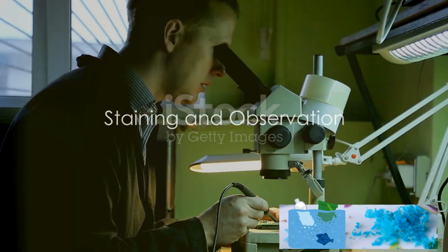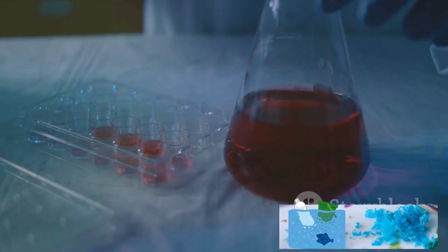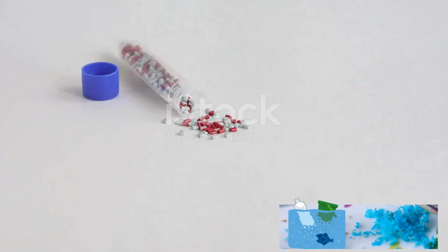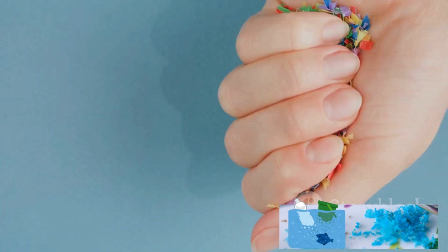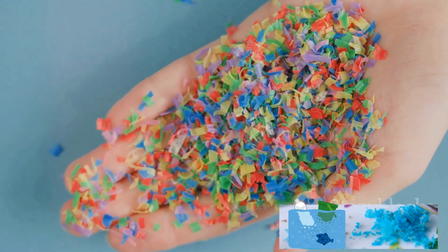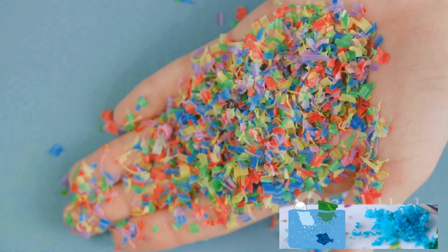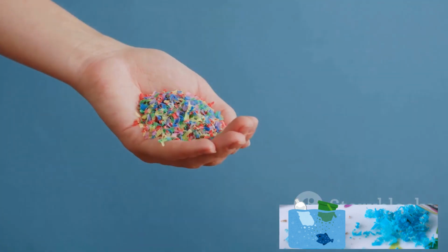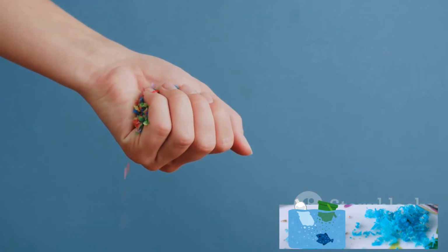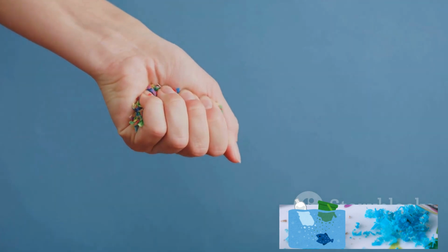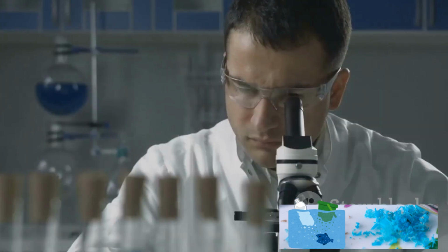Once the filtration process is completed, it's time to move on to staining. The filtered microplastics are stained with a dye known as Nile Red. This dye is lipophilic, meaning it has an affinity for fats and is therefore able to penetrate and stain plastic particles. The staining process helps to make the invisible visible, bringing the microplastics out of hiding.